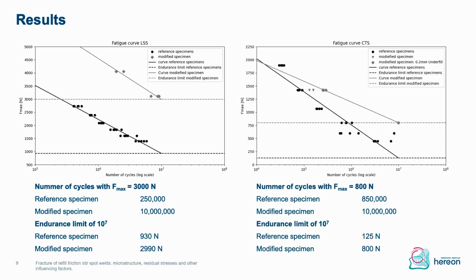In the cross-tension configuration, it's the same. So we saw the reference specimen is again the black dots, while the modified specimens are the gray ones. Here you see also the ones with the lack of refill. This is why we decided to set the underfill of 0.2 millimeters, just to fill it, because then we were able to even further improve the fatigue life. We haven't done that for lap shear because it was not necessary. The results were still very good, but I come to that later.